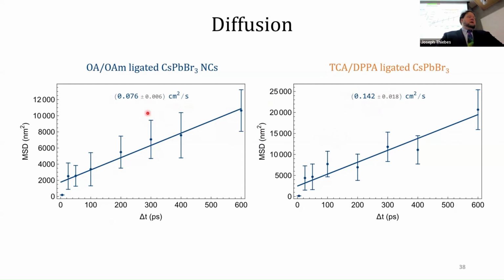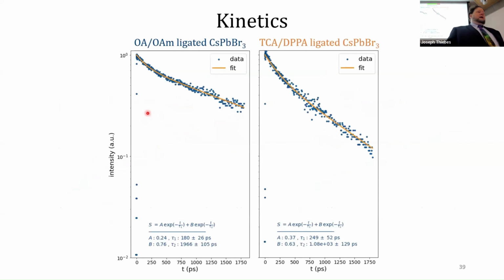So that was encouraging. So we did a bunch more experiments, and we also looked at the kinetics. This is again that decay where we just look at one spot and watch how the intensity of the signal decreases over time, so we're seeing the relaxation over time. And we would expect that if they are delocalizing, there are going to be more interactions between excited states, which may increase the rate of recombination. And we do see that here in these kinetics, where this is happening slower than this. So there's an increase in the rate of recombination.